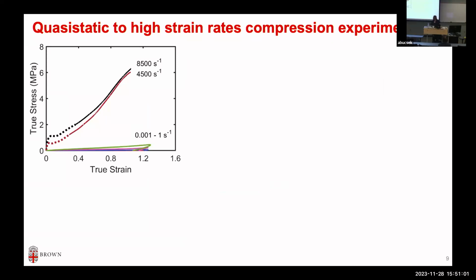But technically, if you do scientific experiments to calibrate, this is a stress strain behavior, right? As mechanics people, we all define our material properties in one-dimensional stress strain behavior. You can see very nonlinear behavior. If you look at the loading curve, unloading curve, you can see nonlinear, then unloading. Some of it is rubber elastic like recovery, but a lot of it is viscous dissipation, more fluid-like. It's a combination of fluid and solid-like.